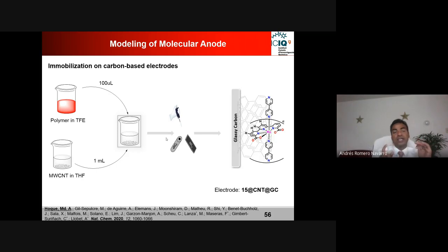What I mean to say is that this is the first molecular catalyst where we are really showing this CH-pi interaction. And I would say that is one of the breakthroughs in our field, showing such a nice interaction and such a stable system. So that's good. We got the molecular system, and we can immobilize it onto the solid surface.